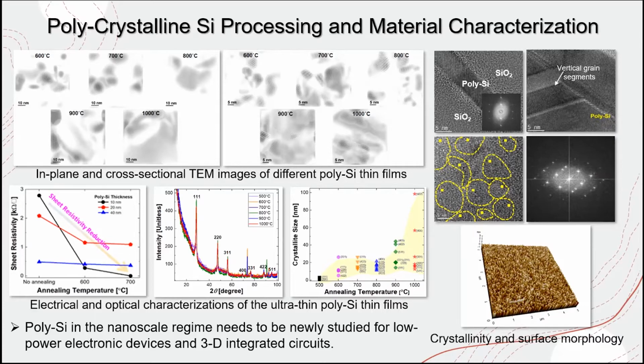So besides the crystalline silicon substrate, the other channel materials can be silicon. If we insist on using silicon, we should take polysilicon, because there's no way to expect crystalline silicon on an interlayer dielectric or inter-metal dielectrics. So deposition and some post-deposition annealing will be the best solution to get some crystallinity to some degree.